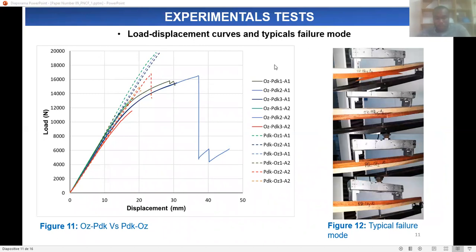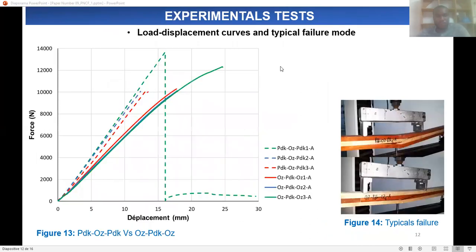Then we have the load displacement curve and typical failure mode of duo specimens, Ozigo-Padouk versus Padouk-Ozigo. For all specimens, stiffness has a small variation. We observe for A1 and A2 configurations a ductile behavior for Ozigo-Padouk and quasi-fragile behavior for Padouk-Ozigo. Last, we have the load displacement curve and typical failure mode of Padouk-Ozigo-Padouk versus Ozigo-Padouk-Ozigo specimens. According to the load displacement curve, the stiffness of Padouk-Ozigo-Padouk is greater than Ozigo-Padouk-Ozigo. We also note the ductile behavior for Ozigo-Padouk-Ozigo and quasi-fragile behavior for Padouk-Ozigo-Padouk.